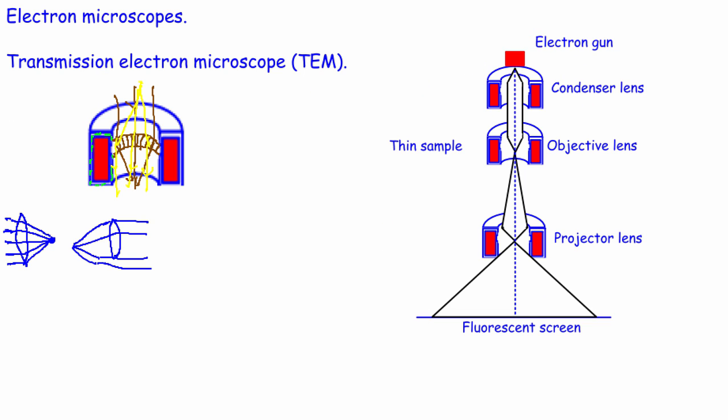So basically what we have, if we switch back to a colour we can see, is an electron gun. That creates a beam of electrons by, unsurprisingly, thermionic emission. And then once we've got these electrons, we accelerate them through a constant potential difference. So what that should mean is that all of the electrons have the same velocity.